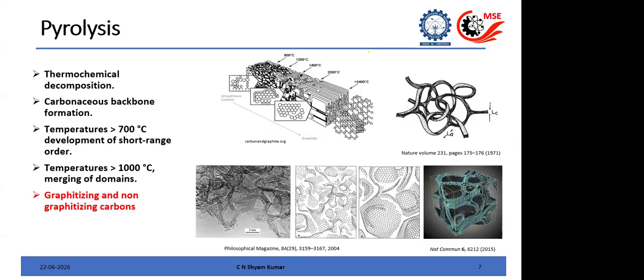It is a thermochemical decomposition, and after the initial removal of volatiles, we will see in the coming slides that a carbonaceous backbone will be forming. This carbonaceous backbone means there will be some aromatic rings or sp2 rings, I would say, which is from the aromatic molecules. And there will also be this disordered carbon, the other carbon which is there. So it is a mixture of initial stages.